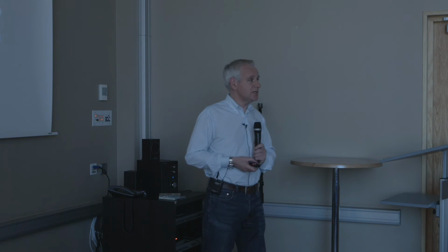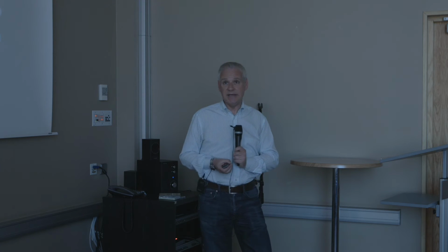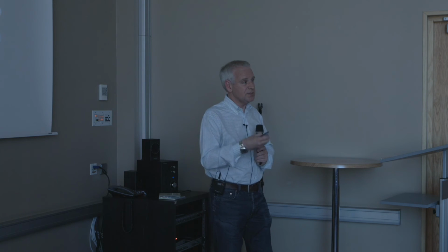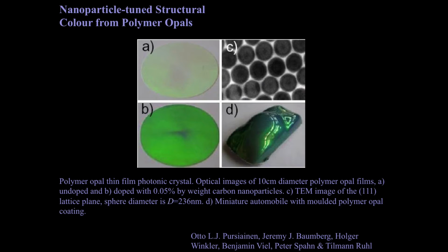And so we're trying to make use of this now. We're trying to copy some of the clever little properties that we're finding in animals, in the ways that the spheres are held together in this case, but also in the amount of black that's in there as well. When we made this by packing together these spheres, it normally was very, very whitish, but we added a little bit of carbon black, and suddenly the wavelengths not reflected are absorbed, and the colour lights up.